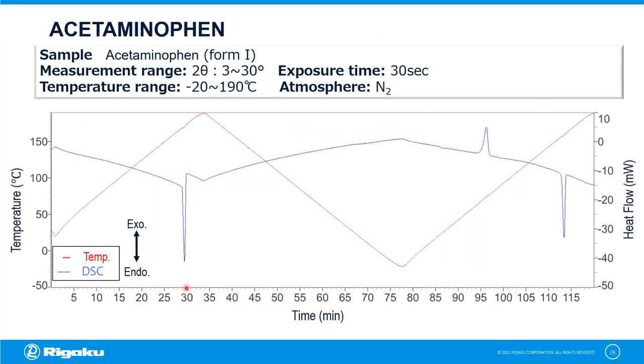So moving on, acetaminophen form one was placed in a crucible in the XRD-DSC sample chamber. We measured the two theta range from 3 to 30 degrees. Each exposure diffractogram was taken over 30 seconds. We measured the temperature from -20 to 190 degrees C. We used an atmosphere of nitrogen to preserve the sample. So you can see the starting point here.